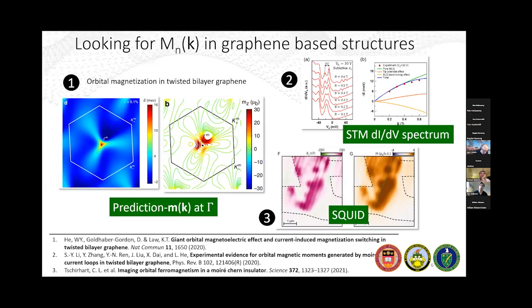Okay, so beyond theory, once this was established, the experiments, first in graphene-based structures, tried to unveil this orbital magnetization in various forms. For example, in twisted bilayer graphene, what I'm showing here on the left is a theory that calculated orbital magnetic moments for this structure that should primarily reside for states near the gamma point. And then several experiments were attempting to uncover these orbital magnetic moments. So here there's one also, I believe, on twisted bilayer graphene, where based on the dispersion of these Landau levels as a function of magnetic field, based on their magnitude, one can attribute this to a topological origin, the non-trivial Berry curvature associated with these particular portions of the bands.